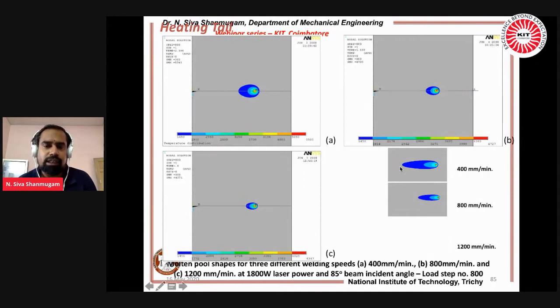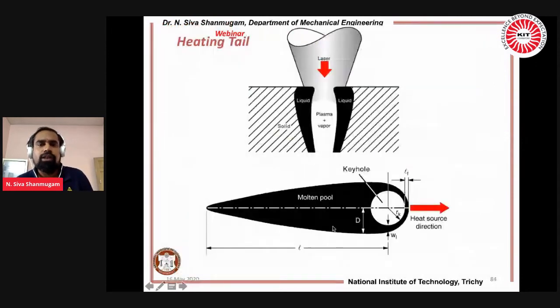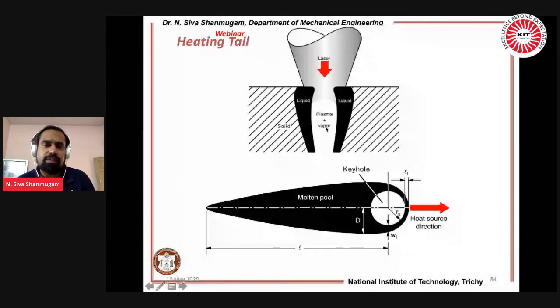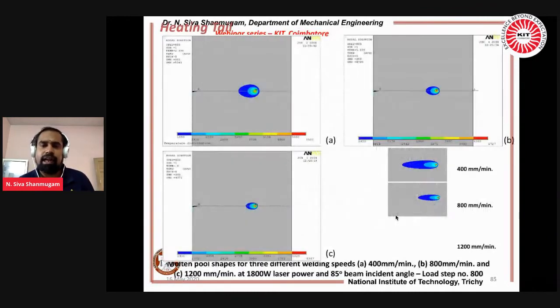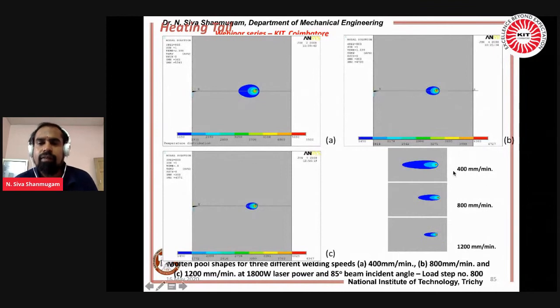What we have discussed here is the molten pool profile and all. So this is the plasma plume. This is something about the liquid part, and this is something about the solid. When you are impinging the laser, after removal, this entire liquid is converted to solid. The keyhole will be filled with the liquid. Upon solidification, liquid is converted to solid, and this profile during the moving of the heat source, you can highlight. You can do the simulation. That is what I am highlighting here with the different welding speeds, how the heating tail looks when you are visualizing from the top.